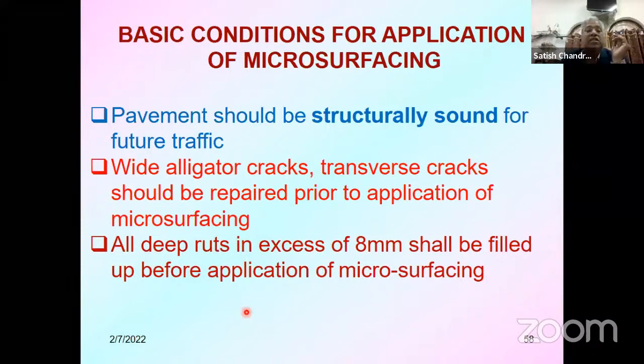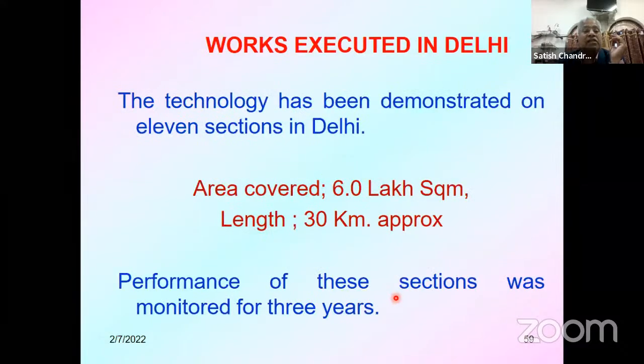Wide alligator cracks, transverse cracks should be repaired prior to application of microsurfacing, and all deep ruts in excess of 8 millimeters shall be filled up before application of microsurfacing, because that is the thickness of the layer, 8 millimeter to 10 millimeter. And therefore, any rut in the pavement, which is beyond this, should be filled up before application of microsurfacing. And as I told you, we have almost laid this microsurfacing on 30-kilometer length in Delhi, and performance of these sections was monitored for 3 years. It is a very good construction.